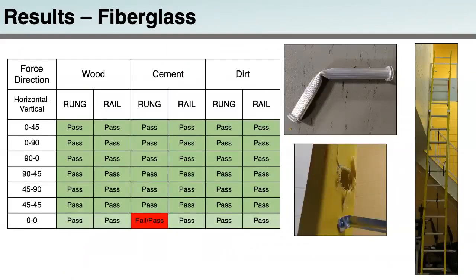When we get into the results to kind of look at and see how these two different ladders, the aluminum and fiberglass ladder, performed, I'll first start to talk about the fiberglass ladder and the failures that we did see. So when looking at the fiberglass ladder, there was only one condition that produced ladder failure upon initial testing. This condition was the dry cement ground surface, the rung tether attachment, so just loop twice around that ladder rung, and the 0-0 force direction, so that straight down drop that I showed you in the videos previously.